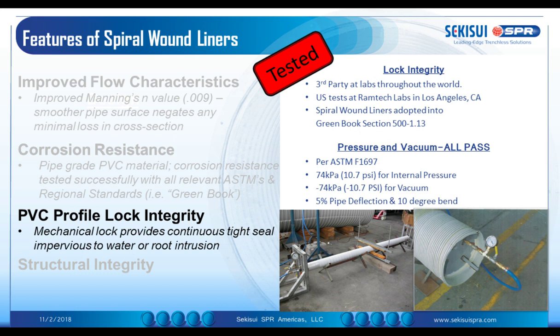The PVC profile lock. Once again, there are a variety of tests that are required around the world. Here within the US, as specified by the ASTMs, there's an internal pressure, hydrostatic pressure, and a vacuum test that is conducted. This requires the liner to withstand a pressure of 74 kPa in a straight orientation, in a 10 degree bend orientation, and also with a 5% deflection applied to the liner in three separate tests for the internal hydrostatic and the vacuum.